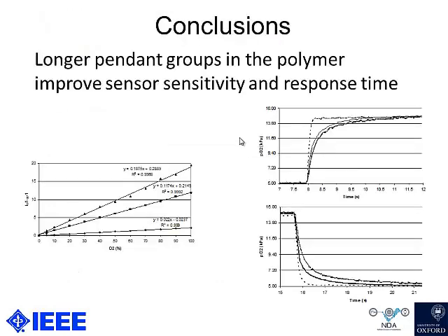Now, as a general conclusion, we think that longer pendant groups in the polymer improve sensor sensitivity and response time. And as a consequence, we do believe that there is a potential interest for their clinical applications, at least in the examples I mentioned at the beginning of the presentation.